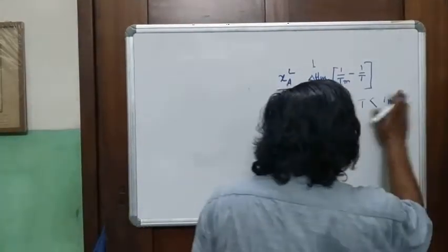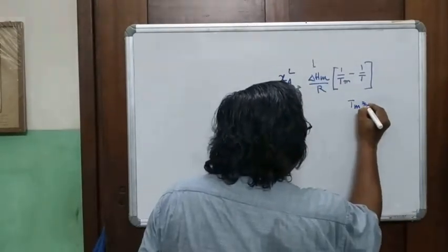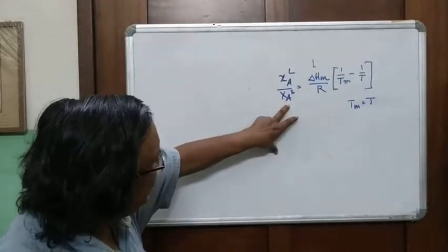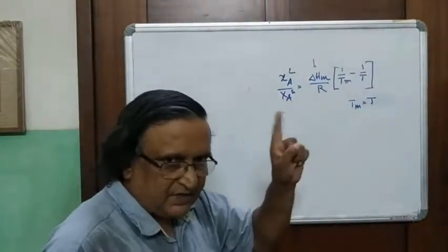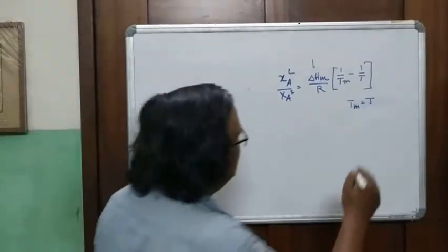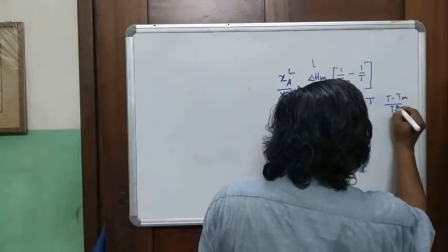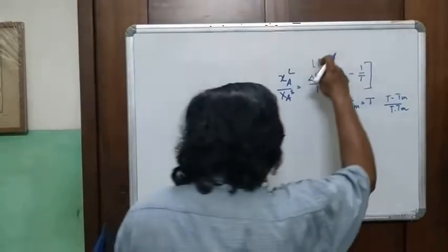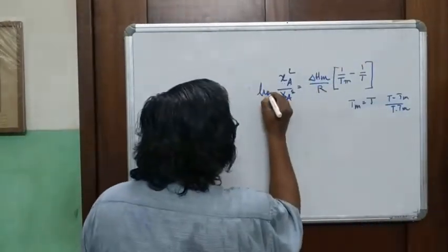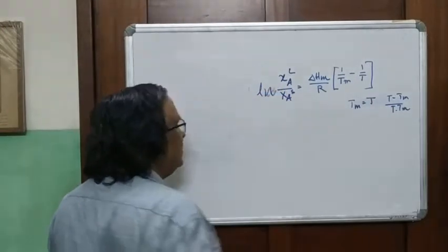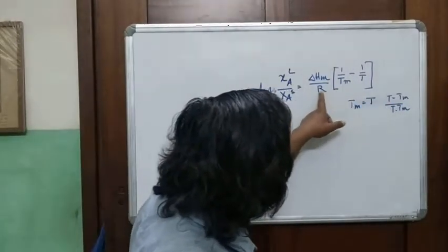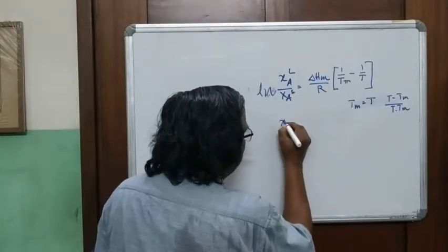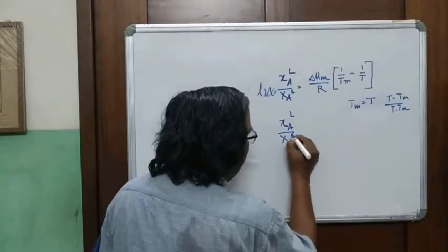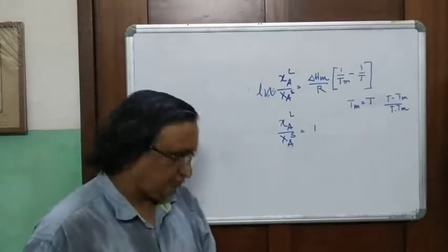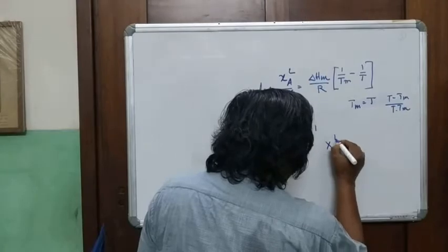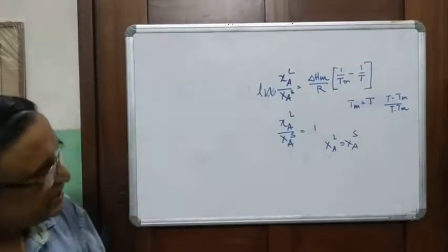Now, if we take again Tm equal to T in this scenario where XAS is not equal to 1. Previously we took it as equal to 1. So for Tm equal to T, this expression T minus Tm by T into Tm turns out to be 0. And so the right hand term turns out to be 0. Ln of this, so if we take T equal to Tm and this whole term becomes equal to 0, then we come to this relationship: XA in the liquid divided by XA in the solid is equal to 1, or XA liquid is equal to XA solid.